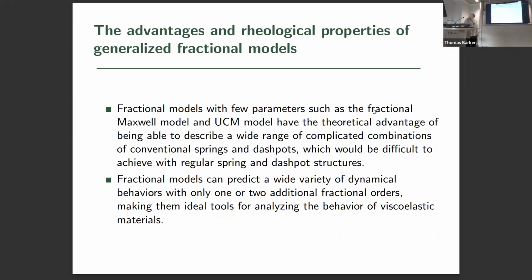Fractional models with few parameters, such as the fractional Maxwell model and the upper convected Maxwell model, have the theoretical advantage of being able to describe a wide range of complicated combinations of conventional springs and dashpots, which would be difficult to achieve with regular spring and dashpot structures. Also, fractional models can predict a wide variety of dynamical behavior with only one or two additional fractional orders, making them ideal tools for analyzing the behavior of viscoelastic materials.